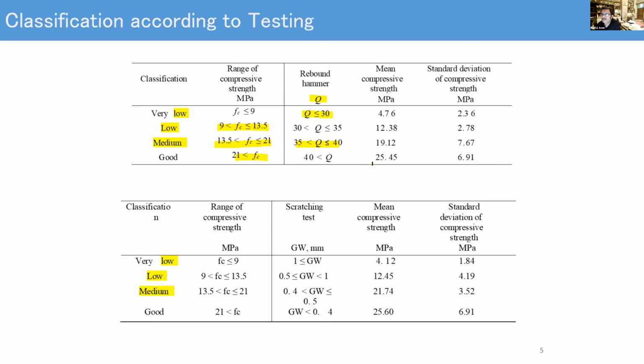From our results, we have seen the standard deviation, and it is quite interesting. You can see here that the higher the strength, the higher also the standard deviation. That naturally means that low strength concretes are confidently really weak, but for high strength concretes there is a scatter. There is a scatter that we have found in our rebound hammer test results in our laboratory and also in the field tests.